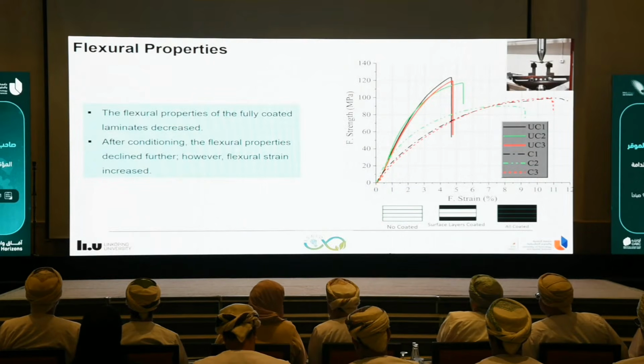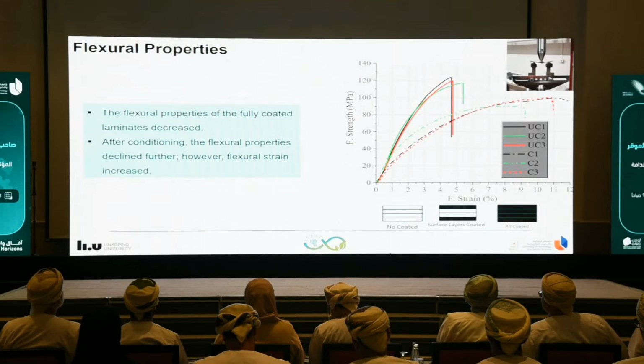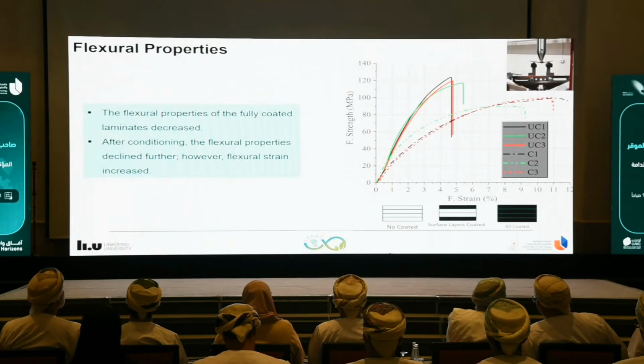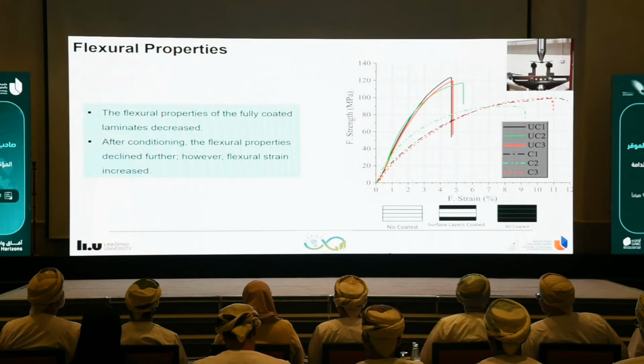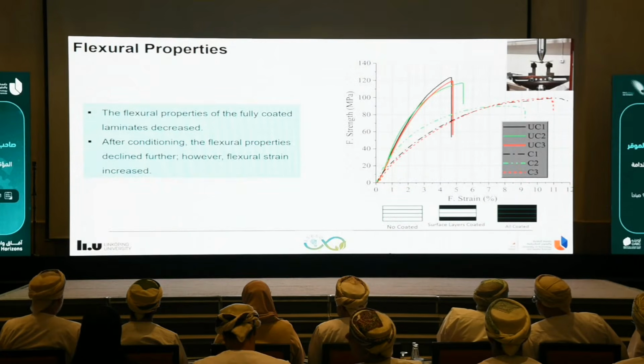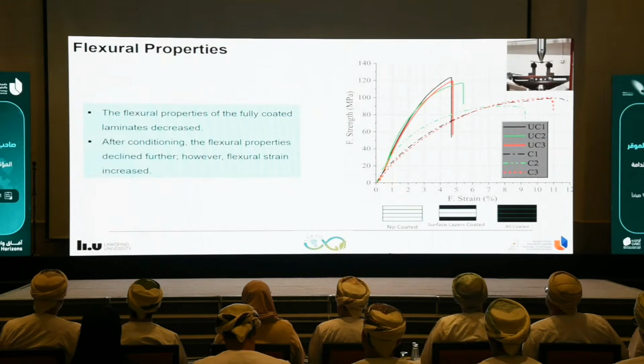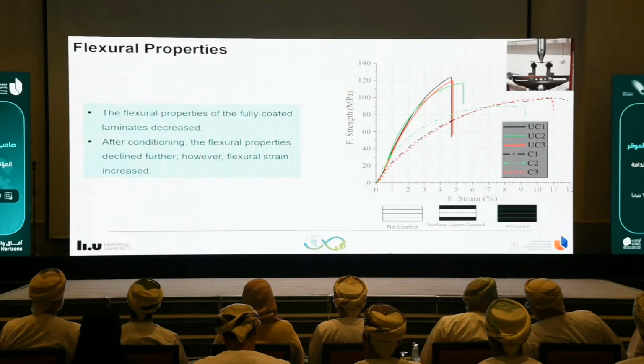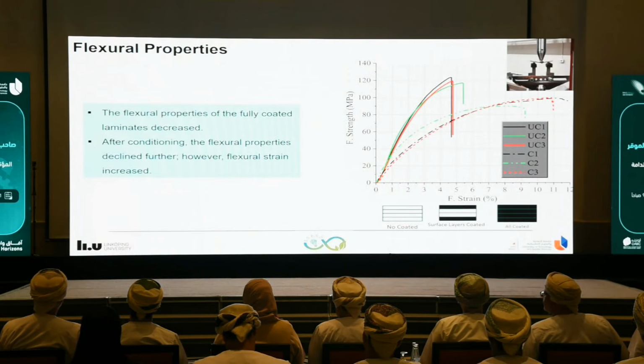We have also performed some mechanical testing to check the properties, and we noticed that after putting the component in water, the dotted lines, the properties go down. So it means that we cannot go further with this type of coating. And we didn't see any increase in properties after coating. So then we decided to investigate this topic more.